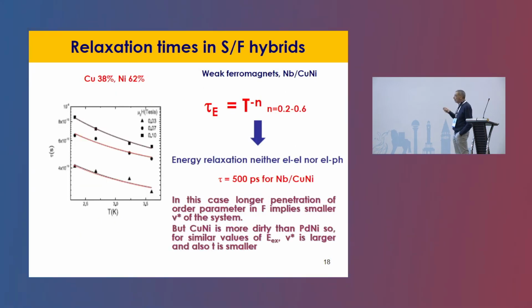Also, the relaxation mechanism is completely different, with an almost constant value of tau as a function of the temperature, which could also be interesting for superconducting single photon detectors, because then the relaxation time is more or less fixed as a function of the temperature, so they can operate more or less. I mean, this is at the same temperature.